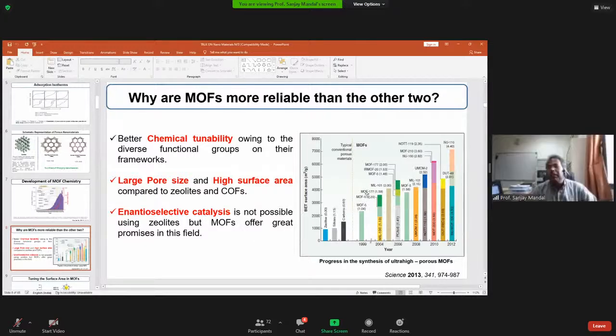The figure right here gives you another important piece of information. On the y-axis, you have BET surface area in meters squared per gram, and zeolite is close to 1,000, silica is about that. In parentheses, you have the pore volume, which is 0.3 in the case of zeolite. But look here, in 2012, something is as large as 7,000, and the pore volume is 4.4. In our laboratory, we got a pore volume over 4.8. I'll show you that picture also.